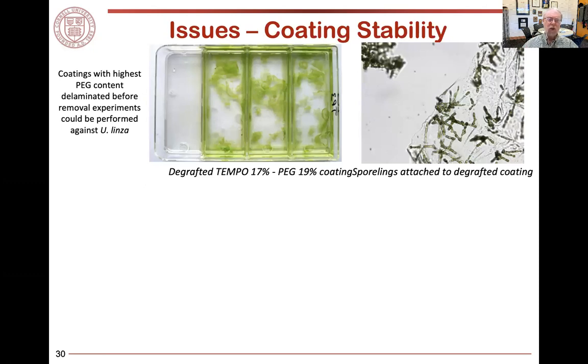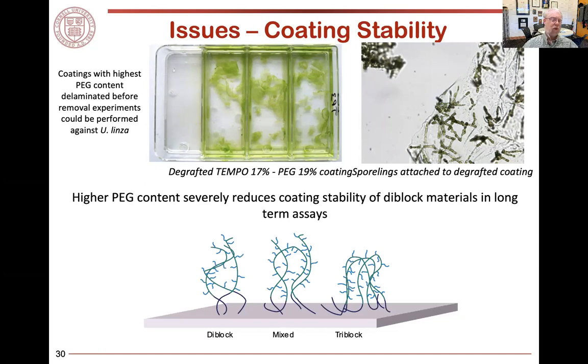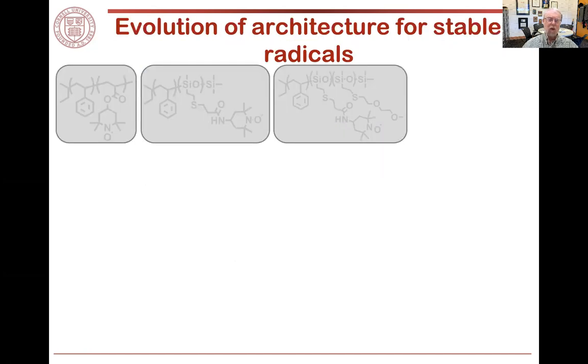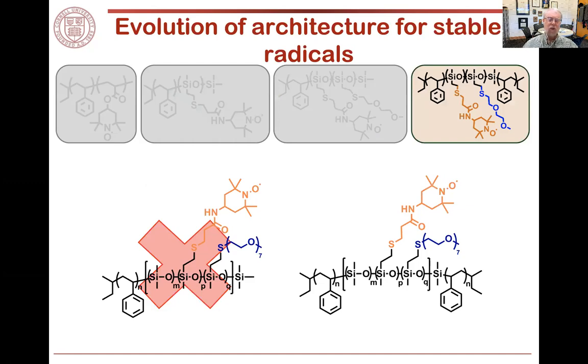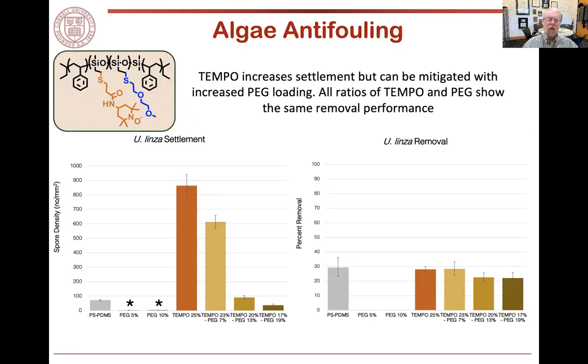But one of the challenges is that the PEG increases the solubility or the ability to be washed off. And so we have, again, this balancing act that we have to carry out. And the natural strategy would be to go from the diblock, which has one linking point, to a triblock that has two. So we have prepared these materials, and we have begun a study of these systems. We know that they attach and form a much more robust, stable coating in water. And if we look at Ulva linza, one of our seaweed, one of our algae test structures, we find that we have a reasonable response to removal of this. So we're getting the effect that we would anticipate from an amphiphilic material.